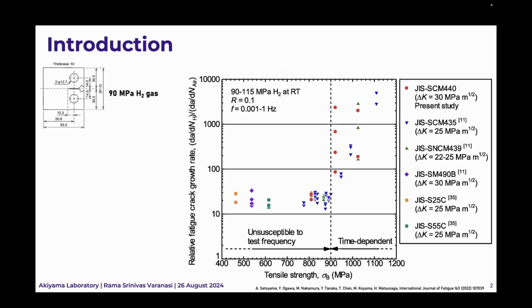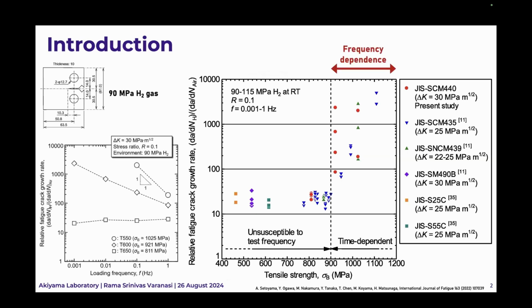In this context, there was an empirical study which showed that when the tensile strength was greater than 900 megapascals, then the relative fatigue crack growth had a frequency dependence. For example, if you look here, this is SCM 440 tempered at three different temperatures, 550, 600, and 650. For the case of 550, the tensile strength is greater than 1000. And we can see that as there is a change in the loading frequency from 1 to 0.1, there's an order of magnitude difference in the relative fatigue crack growth. This is obviously not desirable.